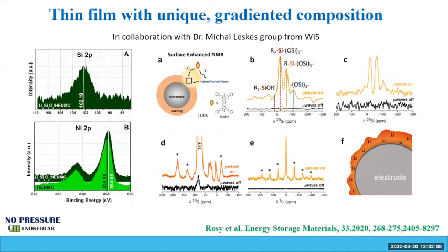We could follow the position of the thin film using XPS, but when you look at the XPS, it was very hard for us to see what the chemistry is through the 3 nanometers, because we could see residual carbon. And it was interesting for us to see if there is a difference from the outer surface of this 3 nanometer thin film. How is it behaving close to the electrode, and what is the environment really far, like 3 nanometers far from the electrode?